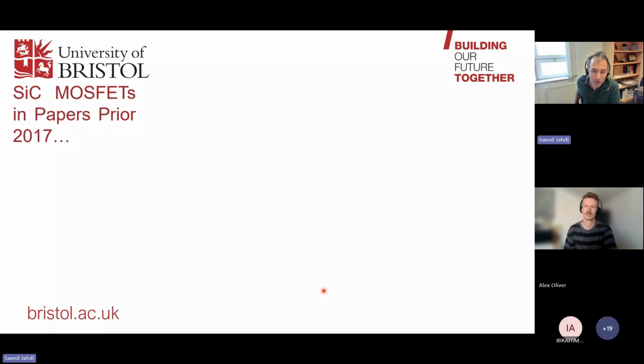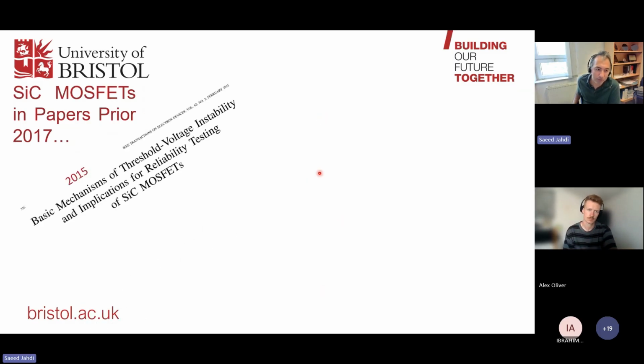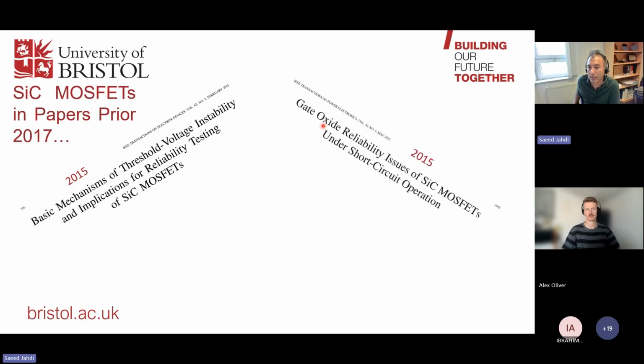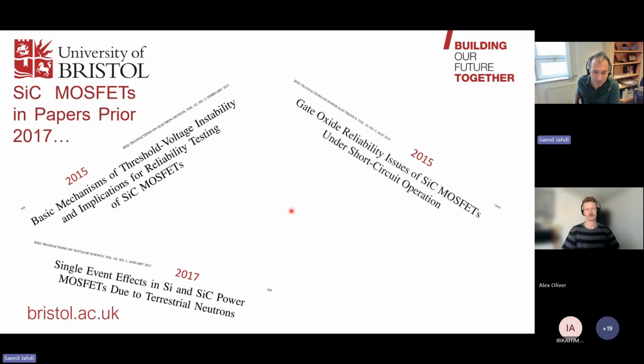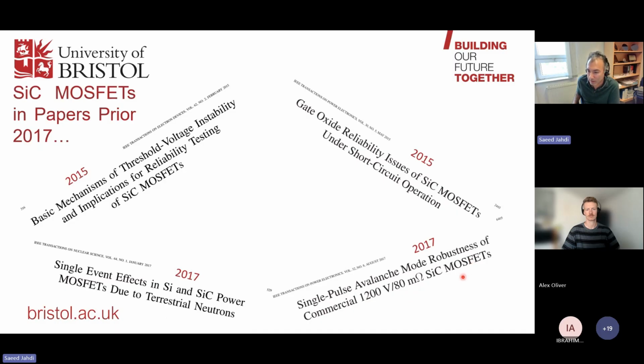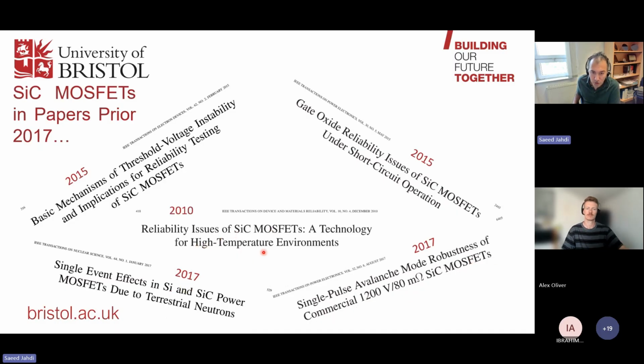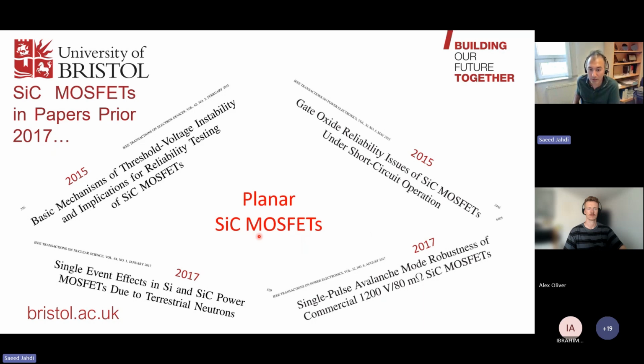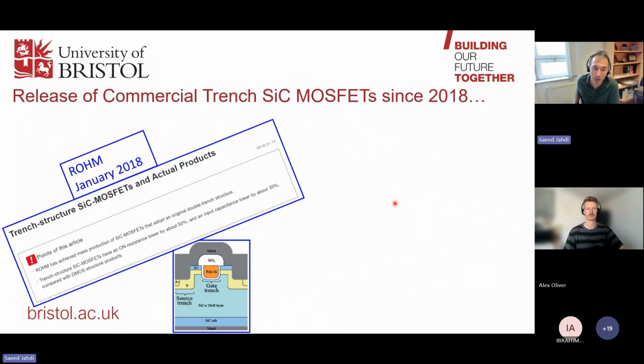If you want to look at the reliability, there are so many papers you can read. I will just mention some of them that are prior to 2017. For example, this one is on basic mechanisms of threshold voltage instability and implications for reliability of silicon carbide MOSFETs. There are others too: gate oxide reliability, short circuit, single event defects, single pulse avalanche mode for silicon carbide MOSFETs, general reliability issues. But what is important is that all of these papers are just talking about silicon carbide MOSFETs generically, because most of them were published in 2017, and at the time, all silicon carbide MOSFETs were planar. So you need to be careful when reading these papers, because of trench devices that have been commercialized more recently, in about the past 5 years or so.